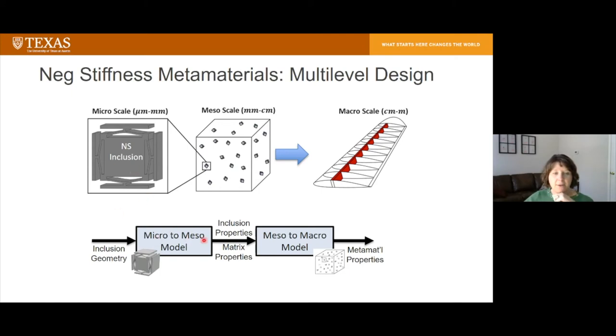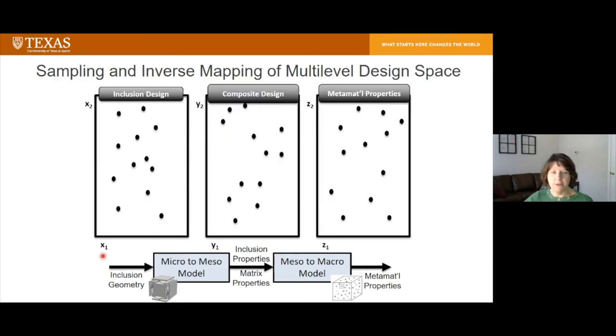And so we have a micro to meso model here that basically determines the effective mechanical properties of these inclusions. Then we have what we call a meso to macro model, which is a homogenization-based model developed by Mike Haberman and his students to treat the matrix and the inclusions as a composite. And from that, we can determine the properties of the metamaterial. But what we really want to do, instead of moving from left to right, which is a very analytical mindset, is to move from right to left. We want a design mindset that says we want these properties. What does the geometry look like?